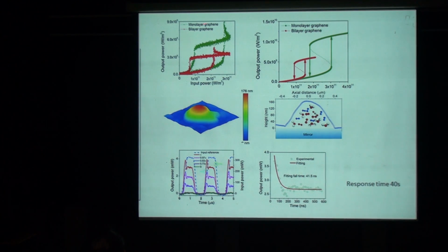Now, we can compare monolayer graphene and bilayer graphene as well. The green line corresponds to monolayer graphene. Bilayer graphene is 2 times. The bilayer graphene has a nonlinear refractive index twice that of the monolayer graphene. So we only need to use half the switching power to achieve resonance, at the same cavity detuning. And the bilayer graphene absorbs twice the amount of light compared to monolayer graphene. As a result, you find that the output power in bilayer graphene is half, because monolayer graphene absorbs less light, so the optical cavity has a higher optical intensity. So it's a very interesting proof that just by changing the thickness of the graphene, you have this very interesting variation.